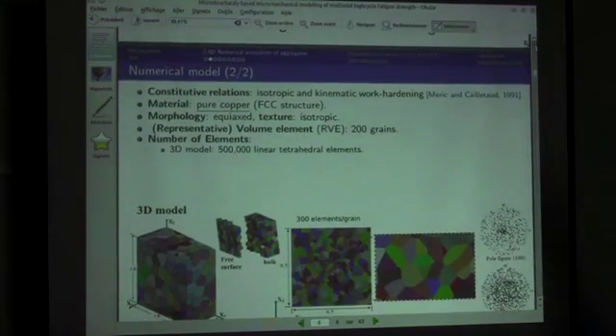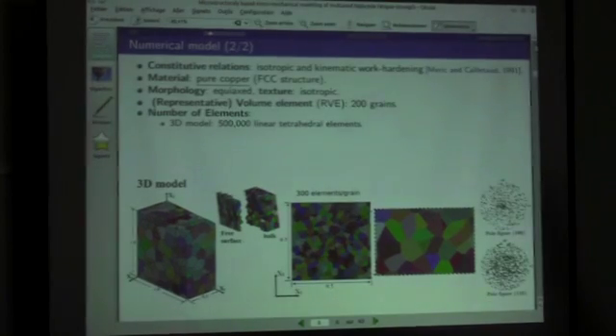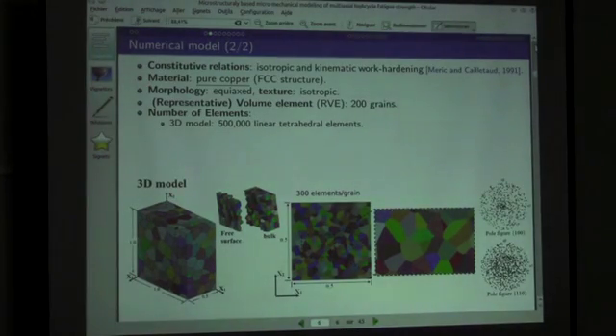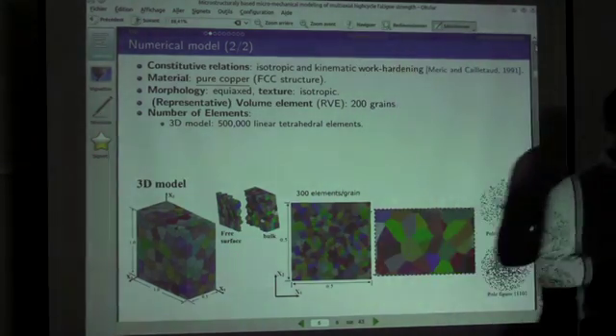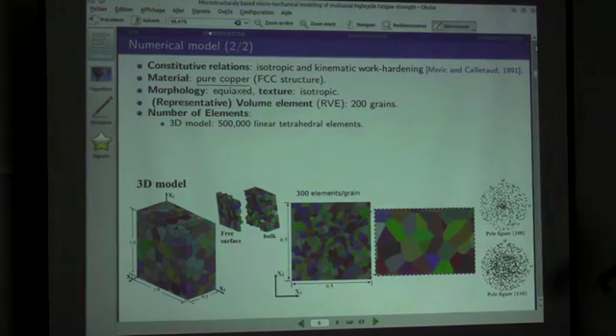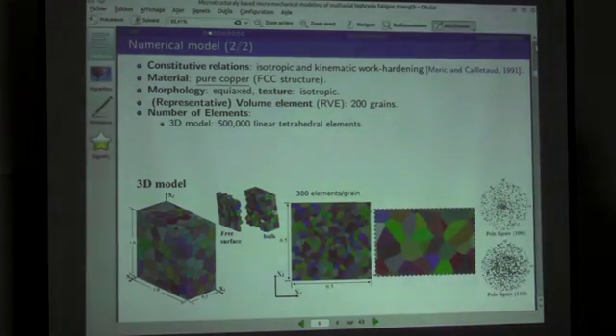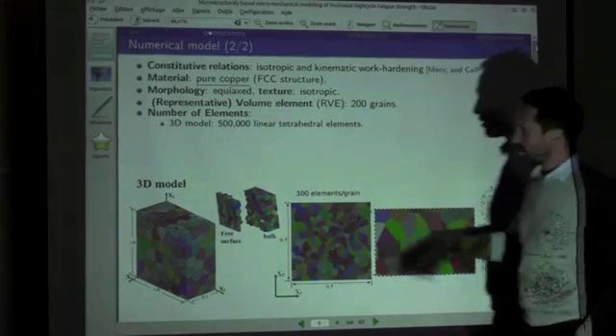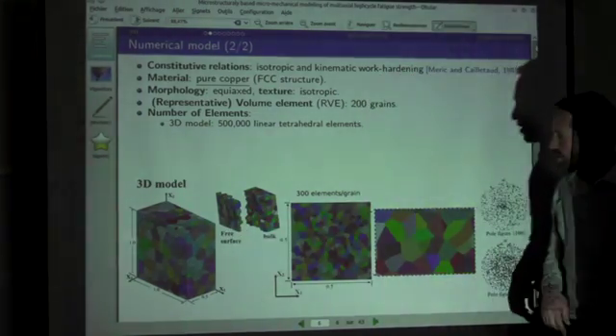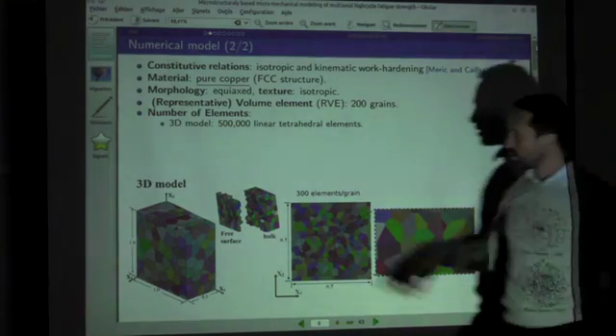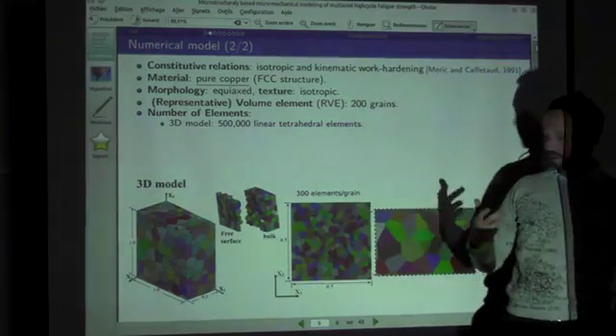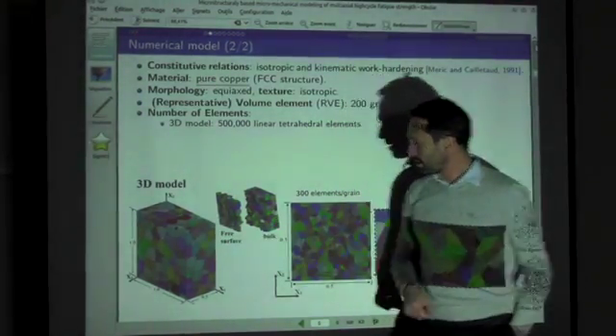So basically, as shown before in the presentation, we use 3D microstructure modeling. We have been using semi-periodical microstructures. That means that you can pave the space with this aggregate to rebuild a larger aggregate. It helps us to avoid some edge effects in the numerical computations. If you use a 3D model with semi-periodical conditions, which means that the sides around are periodical geometrically, but not the front and back sides, then you can analyze some free surface effects, for example.